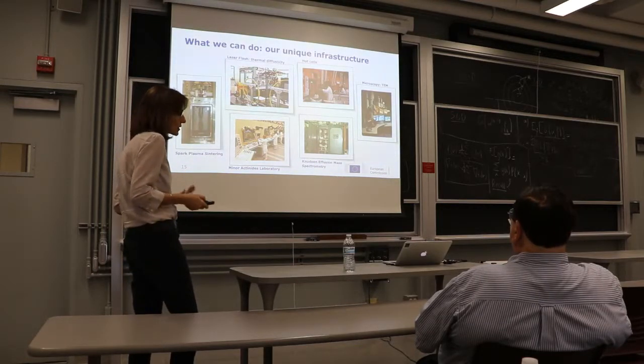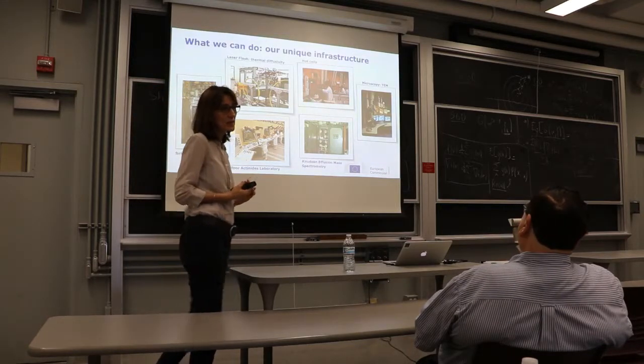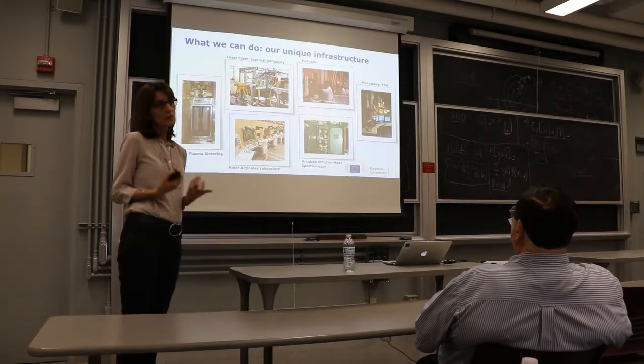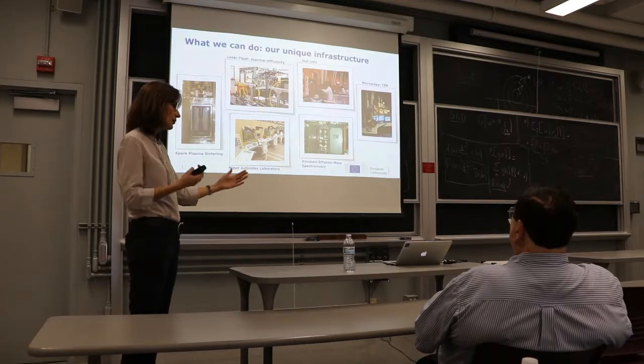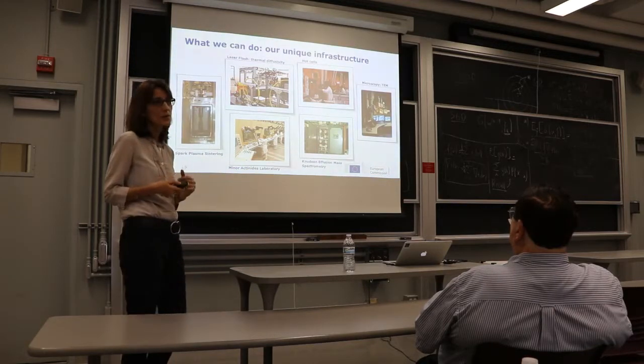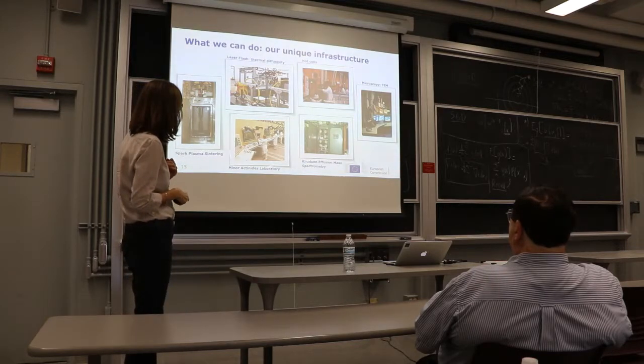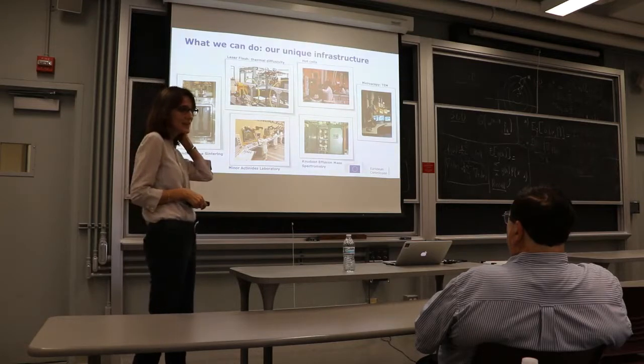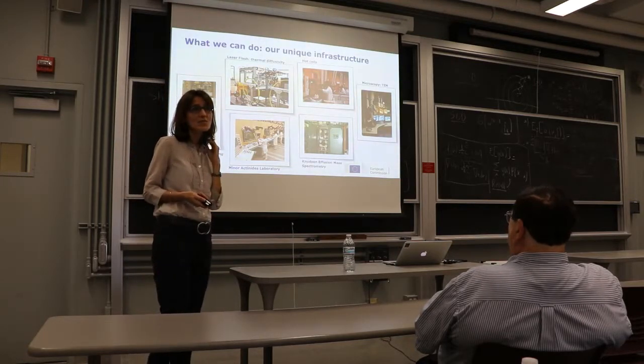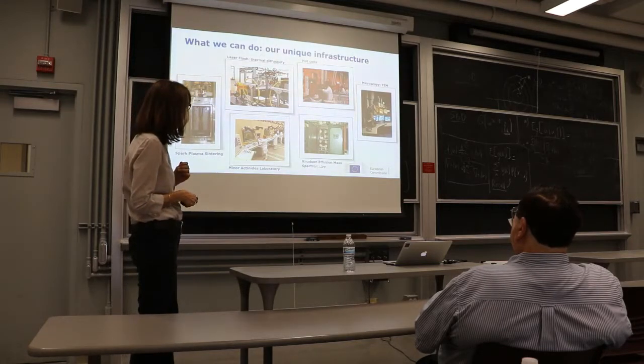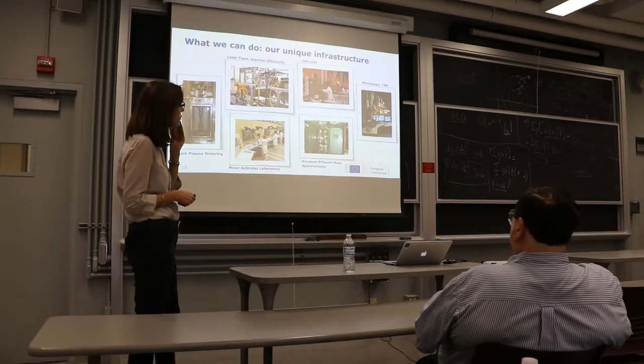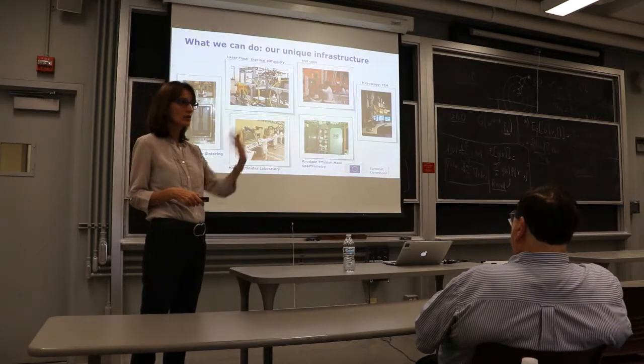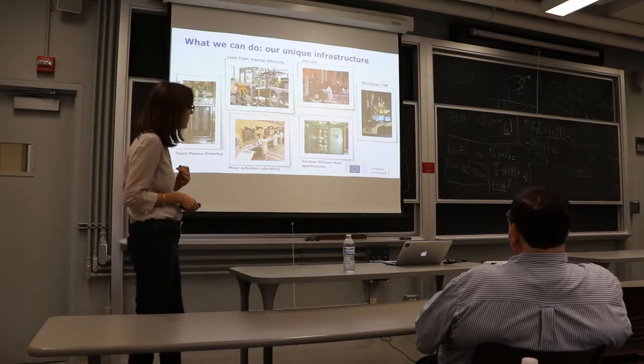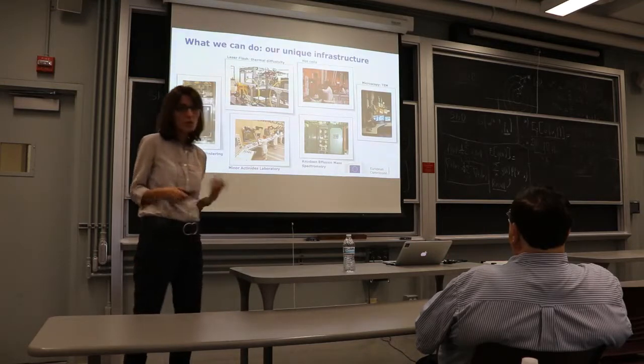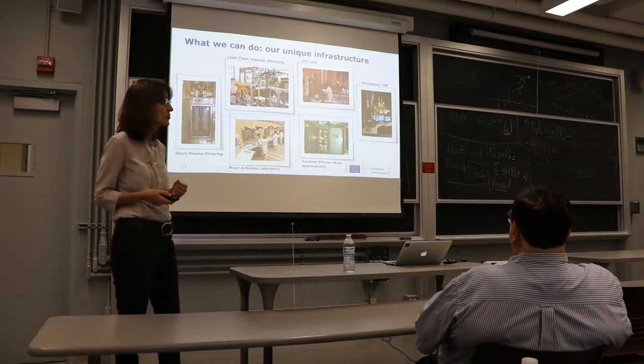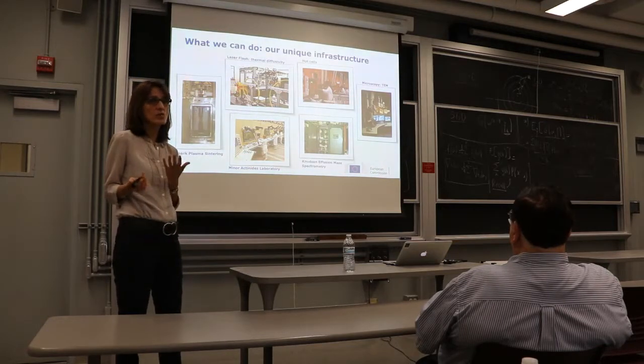The hot cells are very important for receiving the irradiated fuel and even irradiated fuel pins, and then in the hot cells out of the fuel pins or pellets, we can then prepare our samples and investigate the samples. The minor actinide laboratory is relevant in the case of, for instance, the transmutation studies, because we address there the minor actinides. The Knudsen effusion mass spectrometry is very much used, for instance, to measure fission gas release out of the nuclear fuel. And then the transmission electron microscope is used normally, we have also a scanning electron microscope used for normally doing microstructural analysis of the fuel.